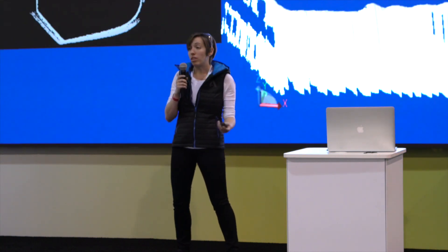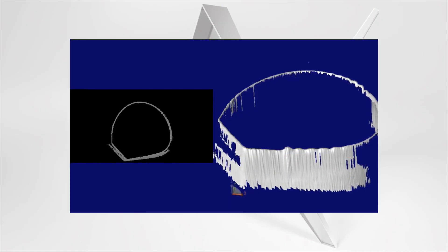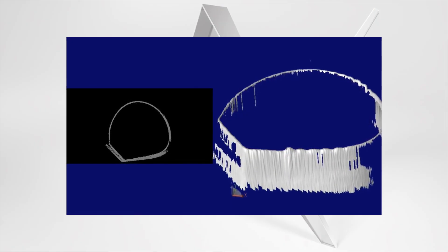We've gotten more sophisticated with things like laser scanners and 3D point clouds, combining all that information so we can tell the robot not only the thing we want it to print, but also how close it's gotten. With traditional printing, the robot only knows where it thinks it should be — now we can tell the robot where it actually is. If the weld is too high, which can happen a lot with this kind of metal, when the weld is cold you might end up with a really skinny, tall weld; if it's really hot, a short, fat weld. All these different variables are unpredictable and hard to account for up front.